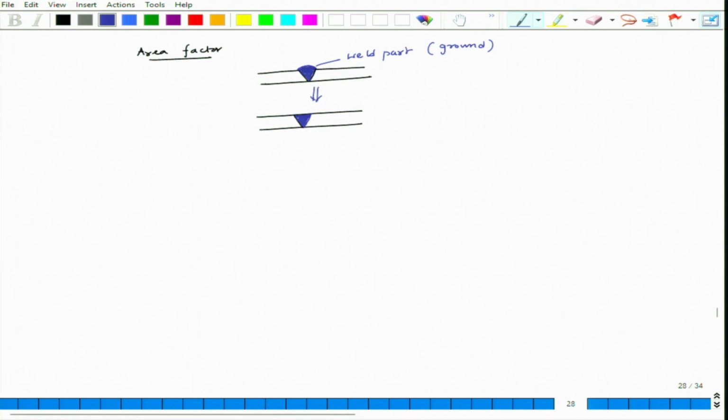So this part here, we have to make sure that this should be noble weld material and this will be active. If it is the same, that's better, but if we don't find the same thing, then it should be active, so that here also large anode, small cathode.